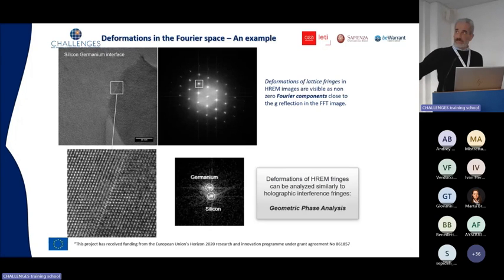What is done here is collect a high resolution image and go to a Fourier analysis of high resolution images. So this is the Fourier transform of the image, and since the image has high resolution, it contains the position of the atoms that are in regular arrangement in the image. There are frequencies that correspond to the lattice planes of the atoms, and these are reported in the diffraction pattern.